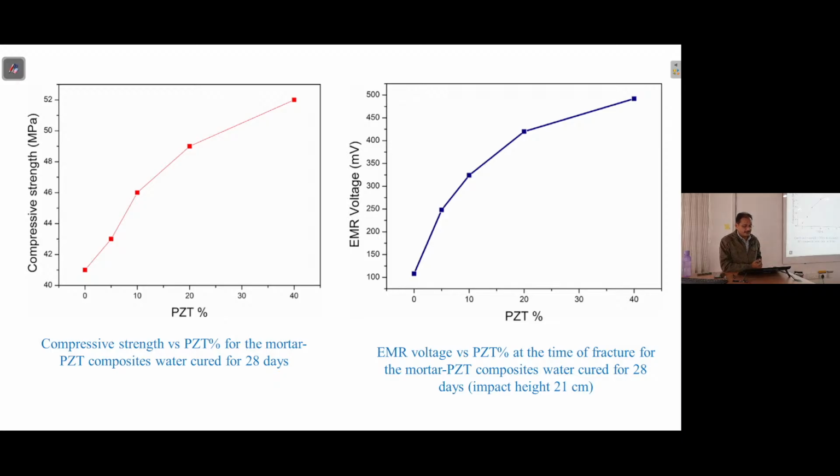And then another interesting result, I would say, is that as we are mixing PZT in these mortar samples, this is actually giving better strength. So somehow it is assisting with the mixing probably, or a better distribution of the hydrated product. So this, in a way, is a promising result, in the sense that